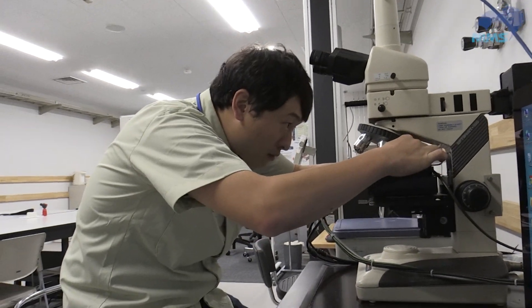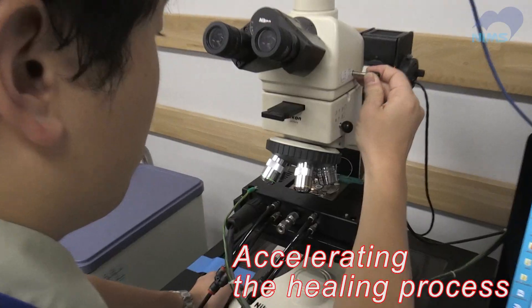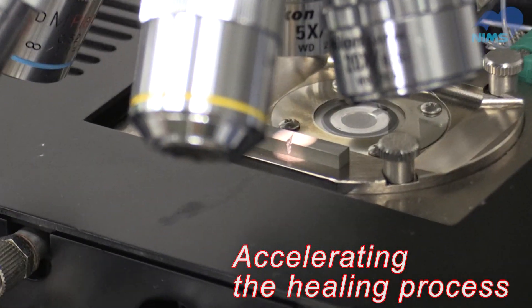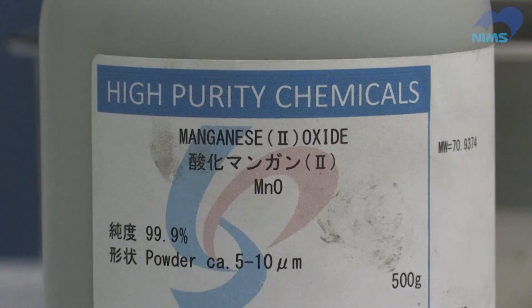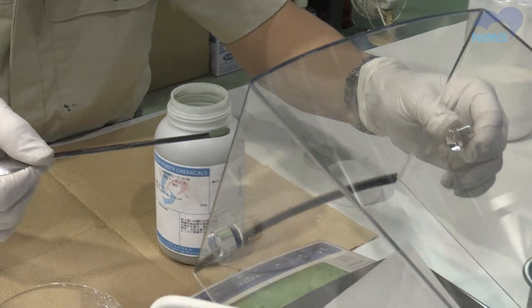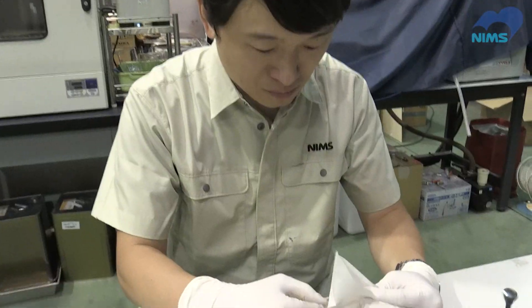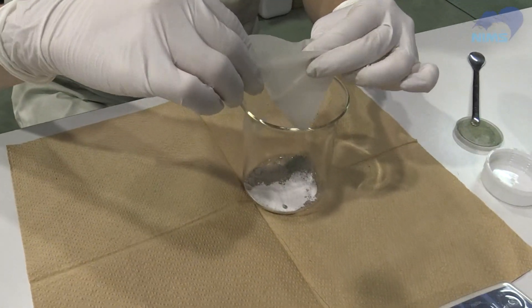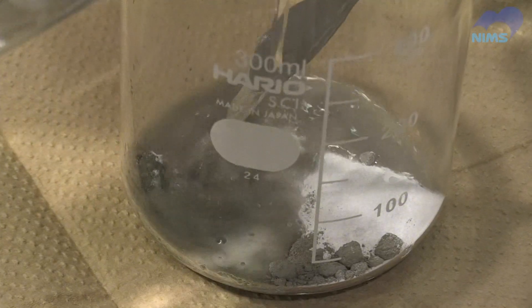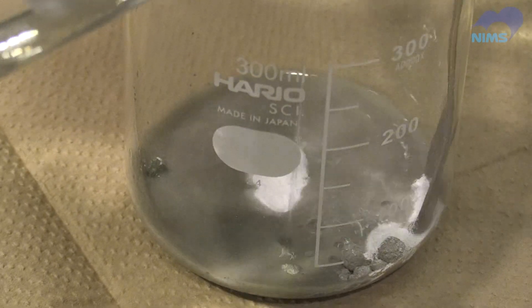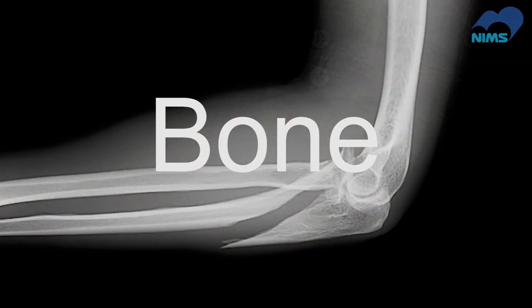Next, Dr. Osada looked for ways to speed up the healing process. He narrowed the target to manganese oxide, because his calculations predicted that it would help generate a supercooled melt at a lower temperature. He created an ingenious arrangement of manganese oxide, inspired again by the bone fracture healing process.